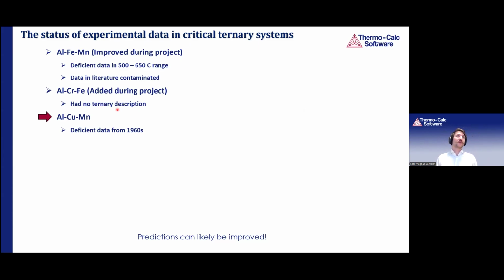Another ternary, aluminum copper manganese system. There's very deficient data available from the 60s. So this is a system where we have an opportunity to create new data. If we can create high quality ternary data, we could rule out some inconsistencies in the old data and improve this system. Aluminum iron manganese system was also improved during this project.